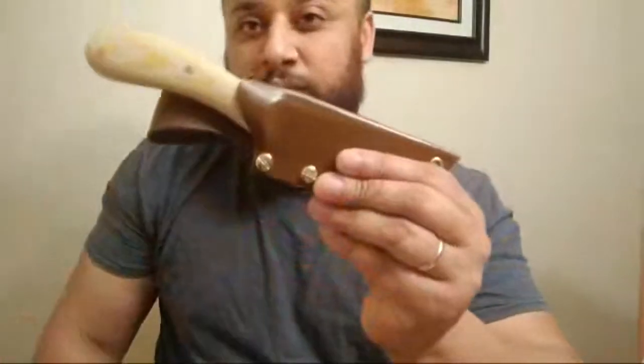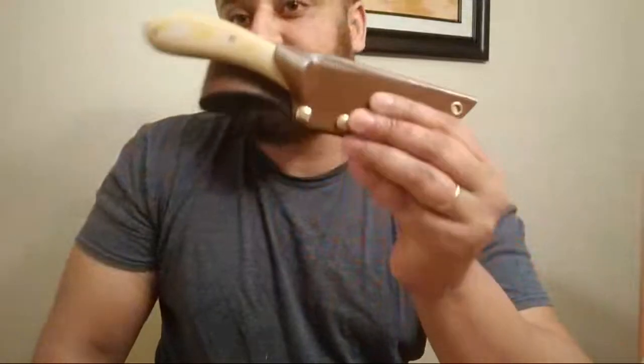But when it came to 15V, what I liked about it was that we had a finer structure, but we had all the necessary carbides that I like, which is vanadium carbide. Is 15V less toothy than Rex 121? Yeah, be real, dude. You need to respect Rex 121. It's 32% carbide volume, dude. It's 70.5 HRC with cobalt in there to help retard the martensite from losing its shape, etc. You need to respect this steel. Rex 121 is a top dog. But what I'm getting at is that it's always a trade-off. Some of you guys are so single-minded about everything.